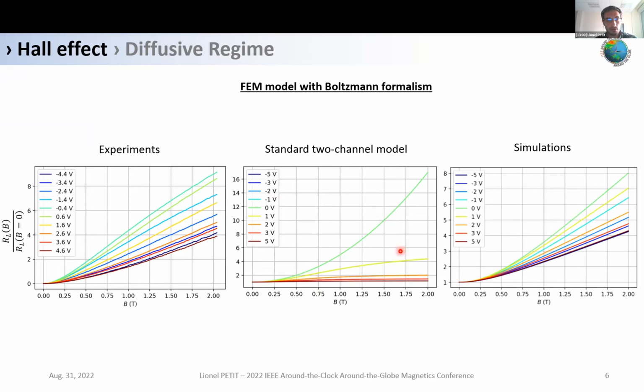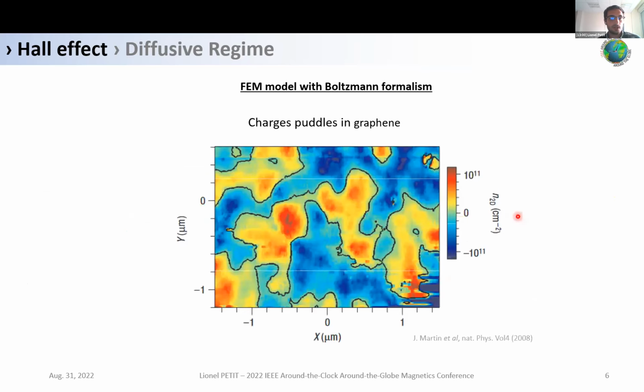But with our model, we are able to apply a gate voltage which is position dependent. And if we simply add a random position-dependent gate voltage, we can retrieve this linear behavior. And it has a physical meaning because when graphene is low doped, it is strongly influenced by its environment. And due to that, we do not have a uniform doping of electrons and holes, but we have puddles of electrons and holes.